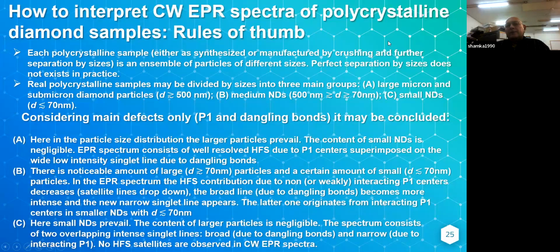Now we have very, very clear rules for how to interpret EPR spectra of polycrystalline diamond samples. When you see this spectrum, you have to follow these rules and everything will be clear. First of all, each polycrystalline sample is synthesized or manufactured by crushing, or synthesized as small particles by detonation or something else. Each such sample is an ensemble of particles of different sizes.